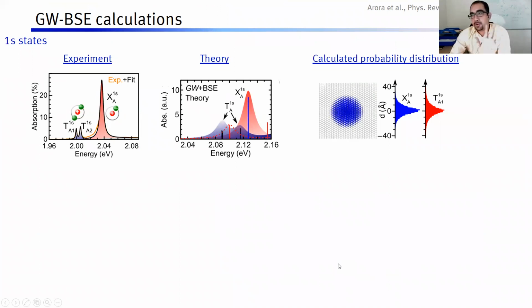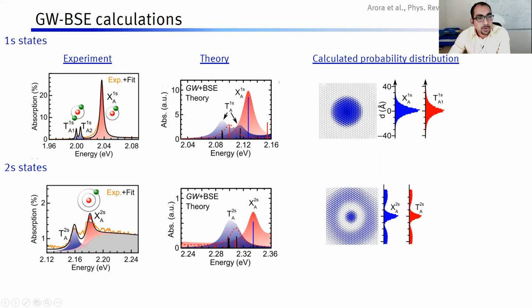For first evidence, we go to our theoretician colleagues who know how to calculate the spectra using GW-BSE theory, which is essentially a density functional theory plus Coulomb interaction on that, plus some other corrections, self-energy corrections on that. And then they find that in the place where we are seeing trions, there should be two trions which are bound. And they should be 1s-like. The wave function is 1s-like. Probability distribution is 1s-like. However, just below the 2s exciton, there should be two types of trions again, which should be bound, and the probability distribution should be 2s-like with a node, just like a hydrogen atom. So they beautifully calculated it, and this is quite convincing.